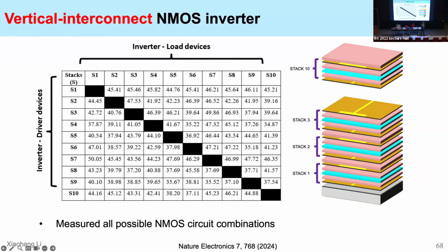For example, today, if you input X amount of watts into a computing chip, it actually will consume more power in the interconnect rather than in transistor switching, rather than the computing itself, right? So this is a significant drawback of only a single stack of transistors as well. So by actually stacking transistors on top of each other, we can realize something that the conventional chip cannot do, which is vertical interconnect. What is the distance between our transistors here? 50 nanometer, right? So the interconnect distance can reduce from micrometer to tens of nanometers.